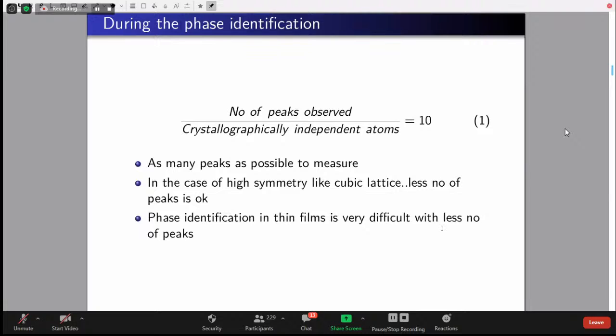Then the thumb rule we give is the number of peaks over the number of crystallographically independent atoms. If you take nickel oxide, let us suppose it is cubic and the primitive cell will have only 2 atoms, nickel and oxygen, just 2. So the number of peaks over the number of atoms should be 10. So obviously we should be measuring 20 peaks. That is the theoretical requirement. Then only can we say that this is the phase.